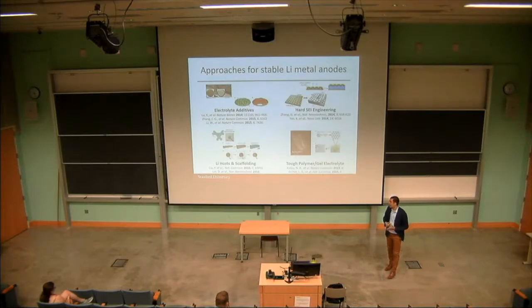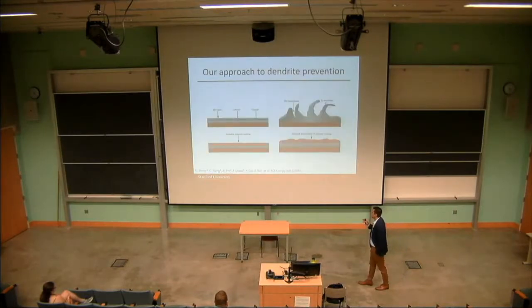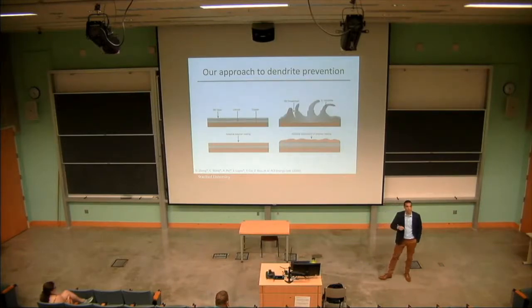And so this motivated a lot of study, people using very, very high modulus polymer materials as electrolytes to mechanically prevent dendrites from penetrating the cell. Our approach is really different than anything that had been done before. Instead of a very, very hard polymer electrolyte material, we went the opposite direction and went for a very, very soft polymer coating.